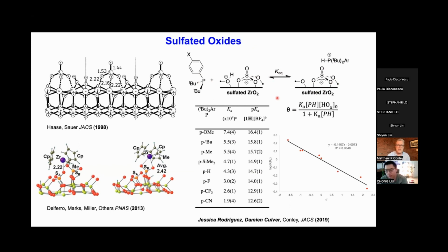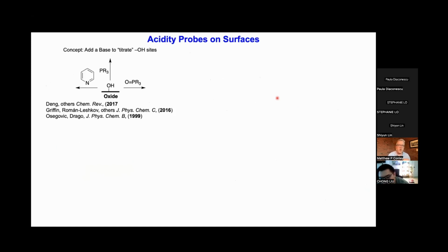So with that in mind, determining the acidity of a surface, which is going to really translate into forming an ion pair or not, is typically done by adsorbing some sort of base to the OH site. I just showed an example with phosphines, and we are not the only ones to use phosphines, though I think we're the only ones who use those complex phosphines. Typically you adsorb PMe3 or something of that type to an oxide, or pyridine while monitoring by FTIR, or phosphine oxides while monitoring the phosphorus-31 chemical shift. All of these are very valuable methods to titrate the OH sites.